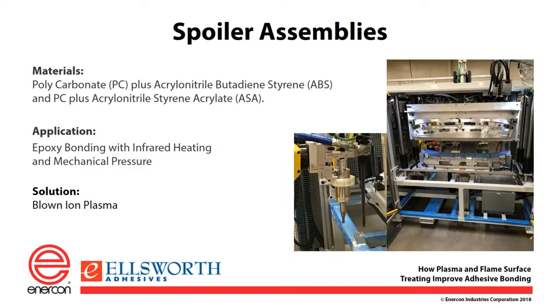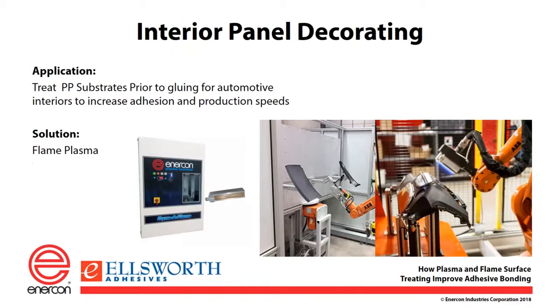Spoiler assemblies is another. If your car has a spoiler on the back or you see them, it's usually polycarbonate plus ABS. You're usually treating it with either a flame or a blown ion. In the picture in the middle, you can see the plasma jet or blown ion jet, and then right behind it, the dark tube is the adhesive being applied. So you can just follow the blown arc with the adhesive and apply it right in line for a quick application.